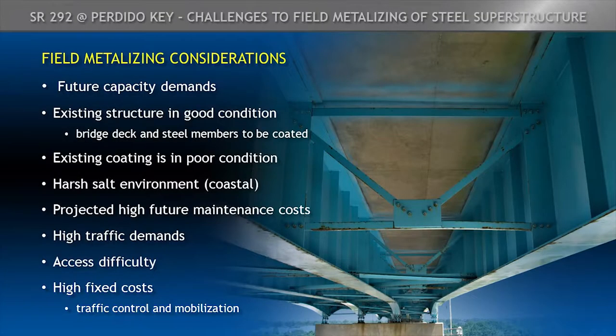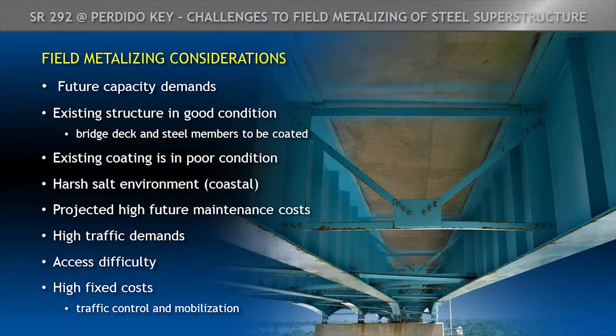We chose field metalizing for several reasons. The future capacity demands are already covered; the growth of the area is kind of stable. We're not expecting this bridge to be demolished and replaced with a wider bridge in the next 40 years. The existing structure is in good condition, including the deck and the structural steel that will be coated. It's just the existing coating is in poor condition and it's reached the end of its service life. The bridge is in a harsh coastal environment. It's constantly exposed to chlorides.